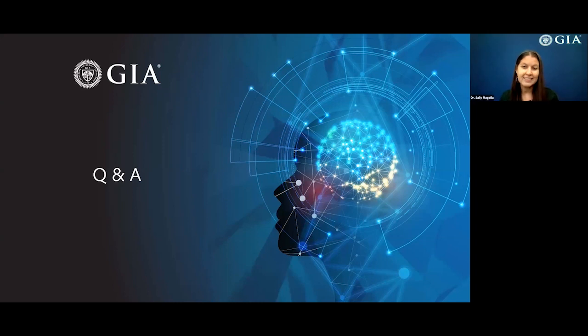Thank you, Aaron. And yes, actually, the violet diamonds that we see out of the Argyle mine, oftentimes those are blue to gray under daylight, and then they switch to a more violet color under incandescent light. The first diamond I showed was a violet diamond that had so much absorption that it appeared fancy black face up. But if it was cut differently, or if it had slightly lower absorption, then you would probably be able to see that sort of color change in one of those Argyle diamonds that often go from, I'm sorry, gray to blue in daylight to violet in incandescent light.